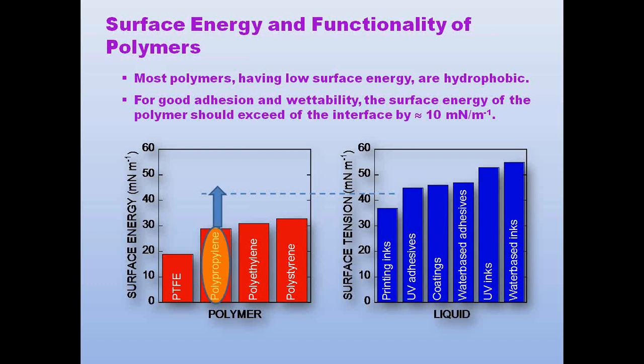If we look at the higher solids content inks, such as UVs and water-based inks, that have very high surface energies, polypropylene must be raised to even higher levels in order to achieve adhesion. And so it's a two-factor equation. One, the surface energy of the base material. Second, the surface energy of the adherent that is going to be critical to create the right adhesion level.